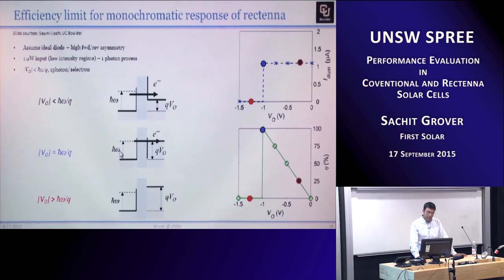When the photon energy equals the developed DC voltage, that's when you're at this point. That's kind of the maximum power point for this IV curve that I've drawn. And as you go beyond in the DC voltage, such that the photon can no longer tunnel across, you do not have any current flowing, and hence no power generation. So this is kind of the ideal picture for rectification in a metal insulator metal tunnel diode. Of course, there are non-linearities. Of course, there are states even below the Fermi level. So that's going to soften the IV curve that you get.